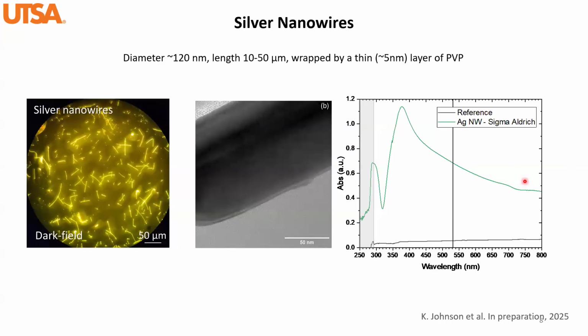So these works are done with gold nanostructures under high pressures. But in our case, since we're interested in propagating surface plasmons, we picked silver because, as I mentioned, silver was the most well-studied plasmonic waveguide at ambient. The silver nanowires we used had a diameter of 120 nanometers and a length of 10 to 50 micrometers, wrapped in a thin layer of PVP. We need that thin layer to create a tiny spacer between our plasmonic structure and the probe molecules I will introduce later, so that we can avoid fluorescence quenching.